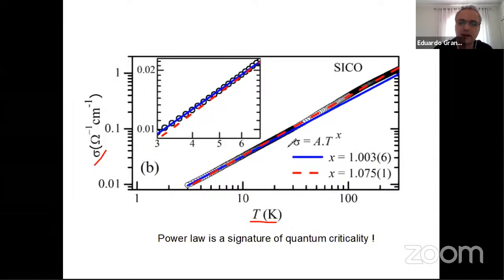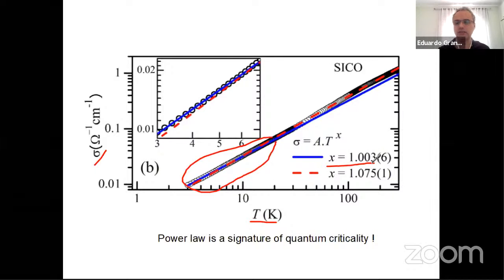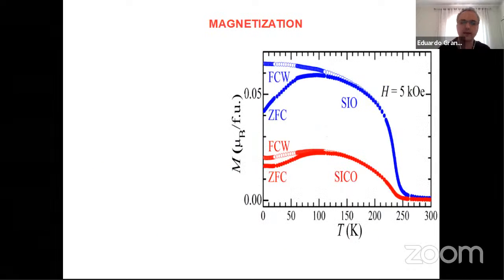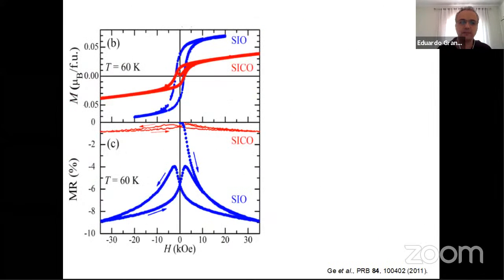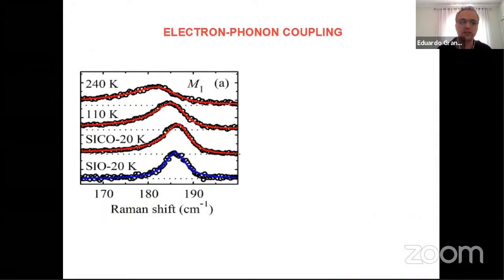And if we restrict ourselves to the low temperature behavior and fit the power law just to the low temperature limit, we have this coefficient, which is very close to unity, x equal 1.00. So it's not only a power law behavior, but the exponent is exactly 1. That's very unusual and very interesting. And because this number 1 is so round, that suggests also a fundamental physics. My time is pretty much up, so I won't get into too much detail about that,